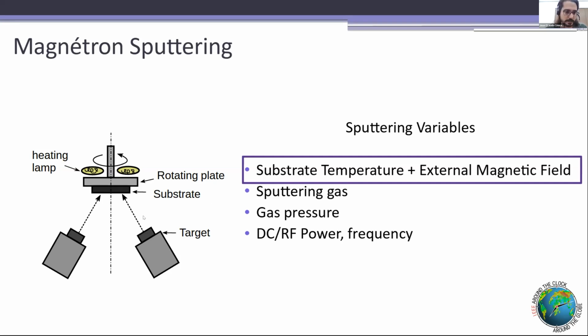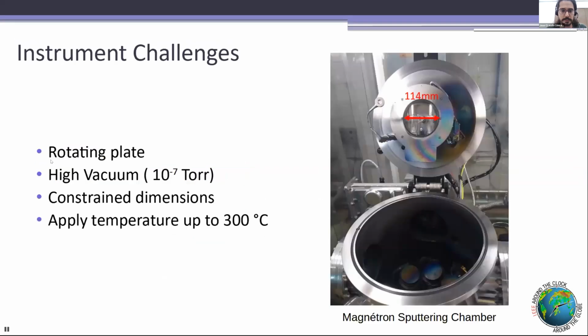So in our sputtering system, we have a target and a substrate and a rotating plate with a heating lamp to increase the temperature. So what's the instrumental challenge? In this rotating plate sputtering system, we have a rotating plate with quite constrained dimensions. It works in high vacuum, and we need to apply temperature up to 300 Celsius.